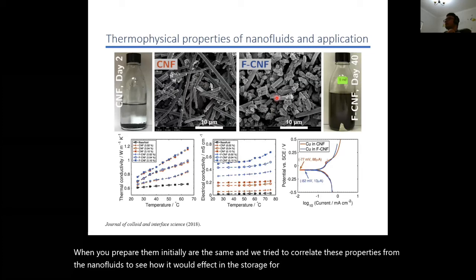Pumping power, not much, but yes, there are sometimes challenges if you use a high volume fraction of the nanoparticle. This is the thing that is happening nowadays, which is foam formation. So for example, when the nanofluid gets heated too much, and if you use a surfactant or something, it would result in foam formation. Another challenge that still needs to be addressed is to come up with practical industrial application. It means to move from the lab scale to industrial scale. So this is one of the challenges that we are